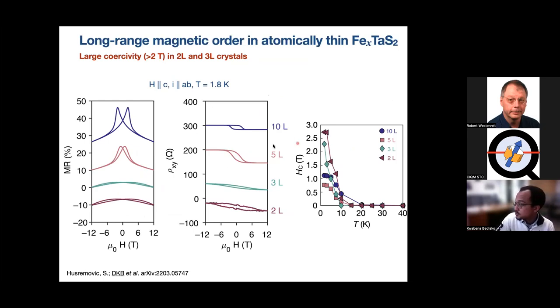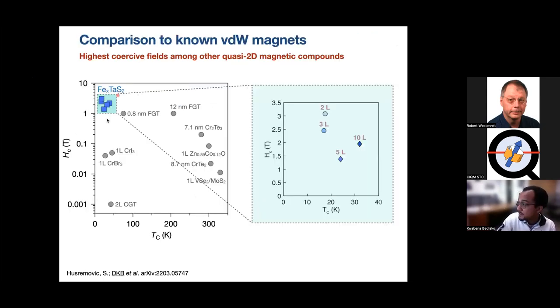And I say 2D magnets, though I had only shown you data from a 10 layer sample. We can get all the way down to the two layer case and show that even for this thinnest limit of this magnetic intercalation compound, sure enough, you see evidence for long range magnetic order and really, really high coercivities, placing these materials as some of the most coercive, if not the most coercive, 2D ferromagnets that we know of to date. And one question, of course, from any application side is, can you get those ordering temperatures higher? But even at low temperatures, there are a lot of interesting fundamental questions that we're starting to ask.